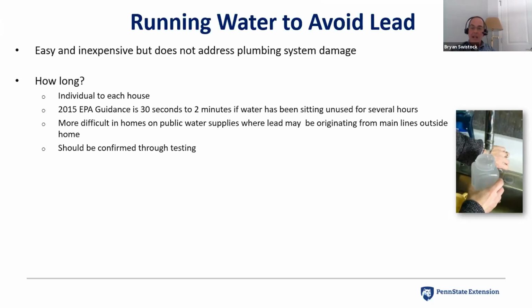But ultimately, this has to be confirmed through testing. You can't rely on this. So we always tell people, try running the water for a minute and collecting a running water sample. Let's compare those. Most of the time that does it. If it doesn't, let's try running the water a little longer and see what that result is. And almost all the time that takes care of the additional lead problems.